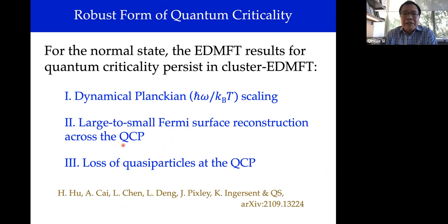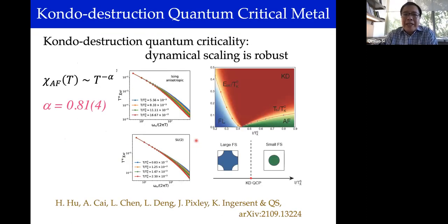And so the first thing we want to check is that in this cluster form of the analysis, the conclusions that we have reached about the normal state, the quantum critical aspect, remain intact. And we indeed show that this dynamical Planckian scaling, the large to small Fermi surface reconstruction, loss of quasiparticles at the quantum critical point remain. So I just want to show the result of this cluster EDMFT calculation for one aspect, which is this E star scale, still collapsed to zero at the onset of anti-ferromagnetic order.